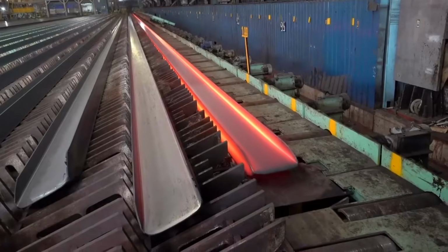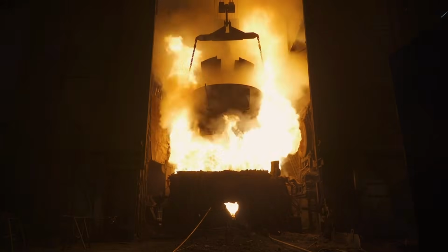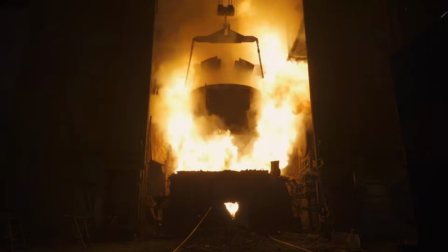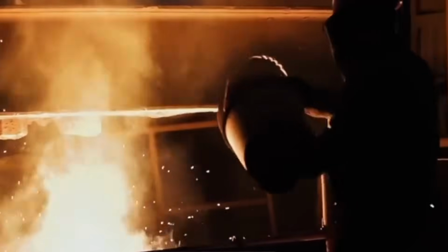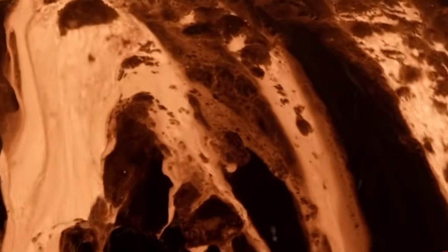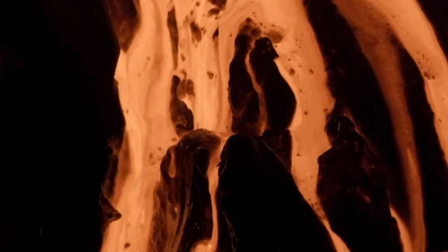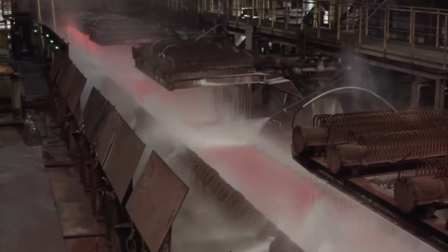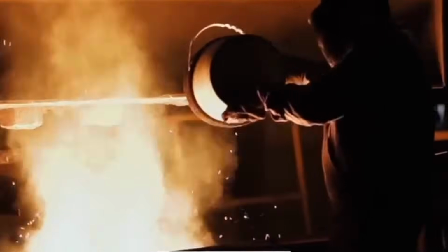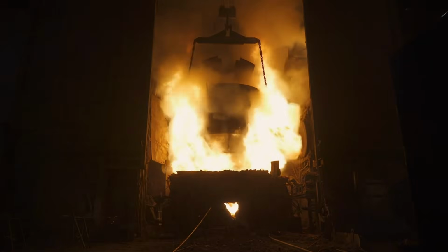The crushed ore moves to steel mills where transformation begins. Blast furnaces, towering over 200 feet tall, mix iron ore with coke and limestone, then blast superheated air through at 3,000 degrees Fahrenheit. The reaction separates iron from oxygen, producing molten iron that pools at the bottom. A single blast furnace produces over 10,000 tons daily, running continuously for years between shutdowns.